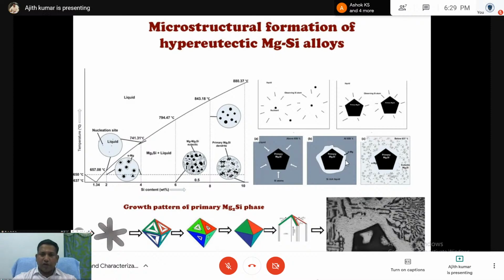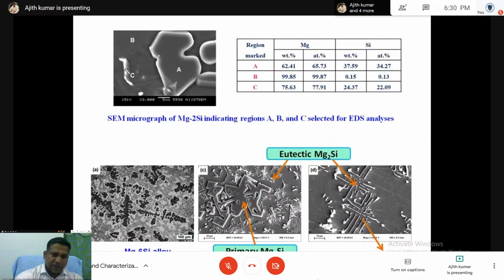So in the surrounded region, when it reaches 657.8 degrees temperature, immediately alpha Mg will form. The remaining will be in liquid condition. When it reaches 637 degrees centigrade, immediately that eutectic Mg2Si will form like a Chinese script or needle kind of structure that we discussed in this SEM micrograph.